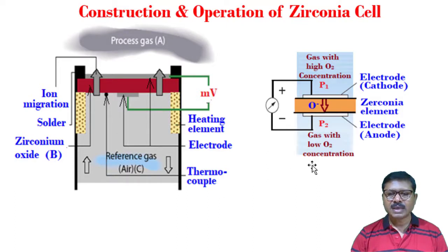This is the cell, the same but a better view. This red color is the zirconium oxide, the zirconia material. At the top, this is one electrode and this is another electrode. This is the heating element, because high heat is required to make the zirconia material conductive. This is gas on one side, this is gas on the other side. Say this is the reference gas and this is the process gas. Now there will be a continuous flow of oxygen ions, and because of the presence of these oxygen ions, a potential will be developed across these two electrodes, and this potential is the ultimate indication of the oxygen concentration of the unknown sample. So this is the zirconia cell. For this zirconia cell, a particular temperature is always maintained by this heating element.